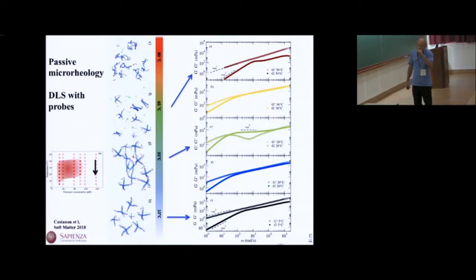You can measure the correlation function with the light, and essentially what you're looking at is the diffusion coefficient, the mean-square displacement of the particle. You can invert the mean-square displacement and get the elastic moduli, G prime and G double prime. And you see, again, the same trend on cooling.